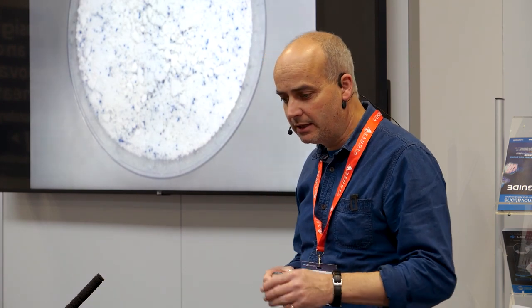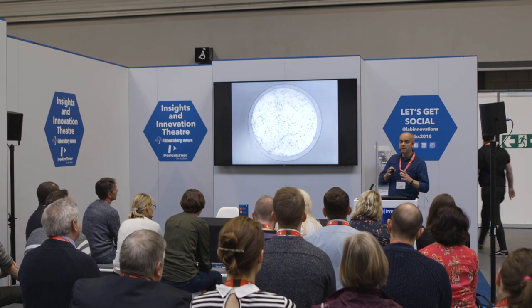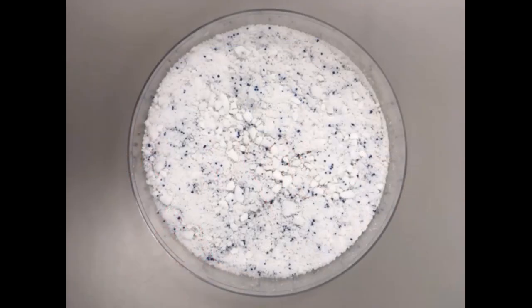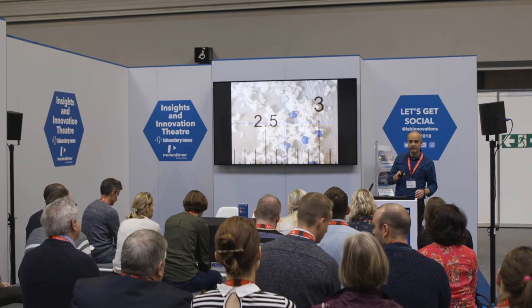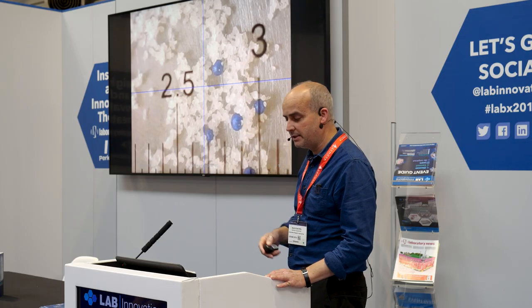In the past we were a little limited by the techniques we had. We had a very small FTIR system, but we were able to look at things like microbeads in personal care products. This is a standard-sized petri dish containing all of the non-soluble material from a typical tube of facial scrub — about half a centimeter or more deep. We thought the blue pieces were probably plastic microbeads, and under micrograph you can see they're very uniform — clearly manufactured microbeads. They're polyethylene. What we didn't realize initially is that all of the smaller, more irregular white pieces are also polyethylene — a huge amount of microbeads in that one tube of product.